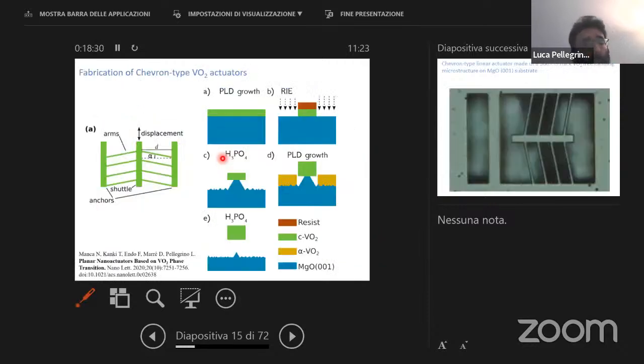I move now to another application of the actuators, exploiting the energy of this film, this material. So we grow the films, we do the patterning by ion etching, and then we grow on top again another film. This is to have a large aspect ratio of our structures, and what we fabricated is what is so-called a chevron type vanadium dioxide actuators. So this is all freestanding. And then when you heat up the systems across the transition, the films will change the lattice parameter. And I will show you now. You can find this in these publications.